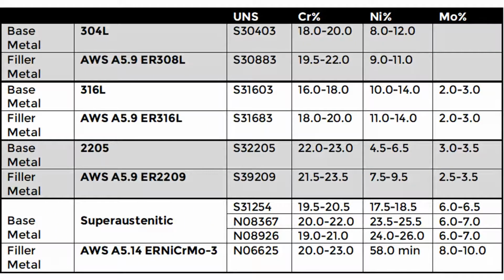This table shows the chemical composition range of the important elements for corrosion resistance in stainless steel grades 304L, 316L, 2205, and superaustenitic stainless steels listed in 3A Sanitary Standard General Requirements, and the chemical composition of the respective filler metals used for TIG and MIG welding.